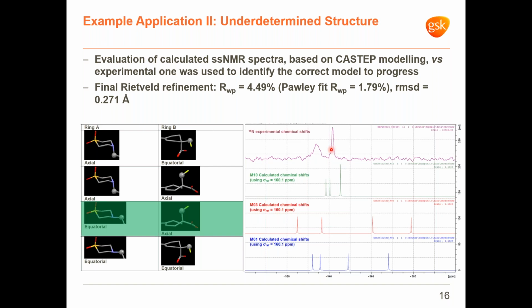So the R factor from the final Rietveld refinement of the M10 solution looks acceptable, though the RMSD is a bit higher than what we would ideally like. Considering the low packing coefficient of the structure, we concluded that a model disorder was likely to be responsible for the observed discrepancy between the CASTEP optimized and Rietveld refined model. But I should say, to date, this is still the best structural model we could obtain for this crystalline form.